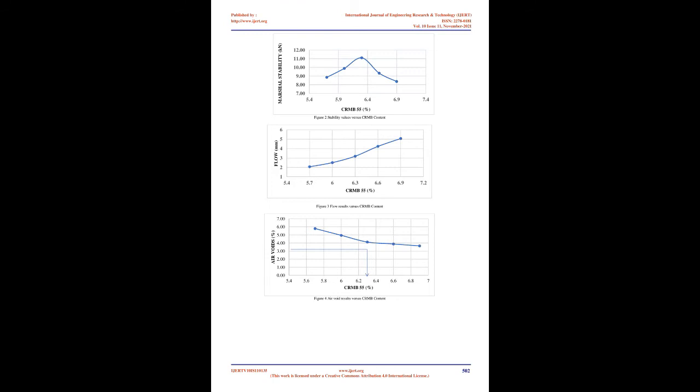In the design of bituminous mixes, the Marshall method of mix design is generally practiced in India. It is a formal design method developed by Bruce Marshall. In this method, the plastic deformation resistance of the cylindrical sample of the bituminous mix is measured when the mix is loaded at 5 cm/min on its lateral surface. Marshall stability is defined as the load carrying capacity of the specimen in kg or kN at the standard temperature